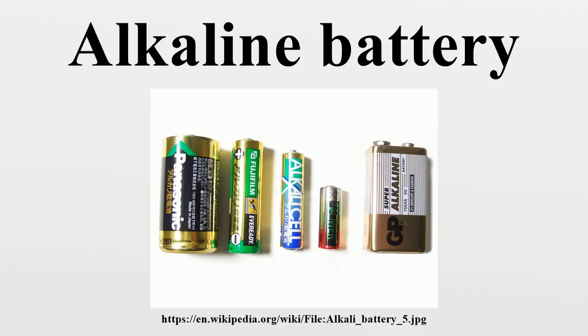Voltage. The nominal voltage of a fresh alkaline cell is 1.5 V. Multiple voltages may be achieved with series of cells. The effective zero-load voltage of a non-discharged alkaline battery varies from 1.50 to 1.65 V, depending on the purity of the manganese oxide used and the contents of zinc oxide in the electrolyte. The average voltage under load depends on level of discharge and the amount of current being drawn, varying from 1.1 to 1.3 V. The fully discharged cell has a remaining voltage in the range of 0.8 to 1.0 V.